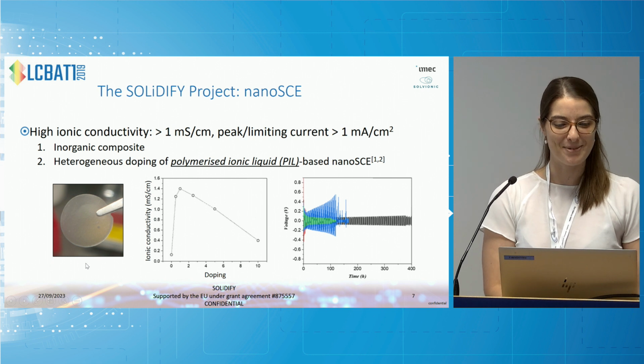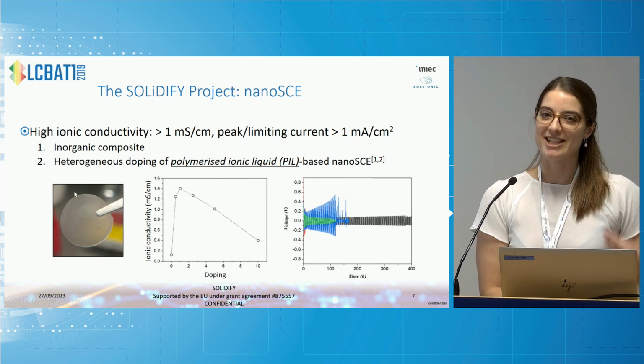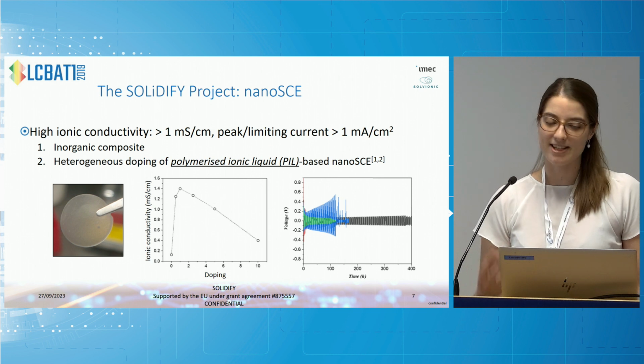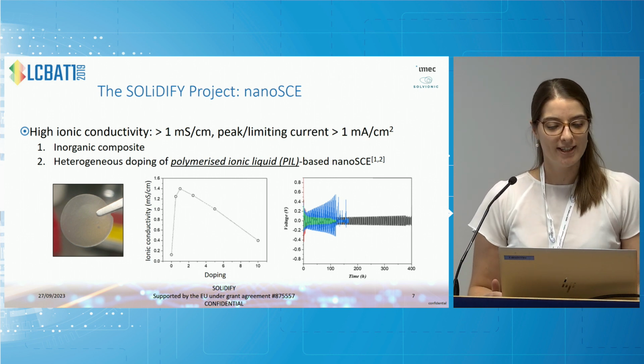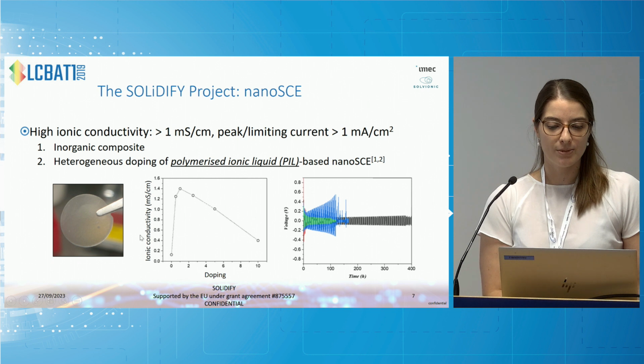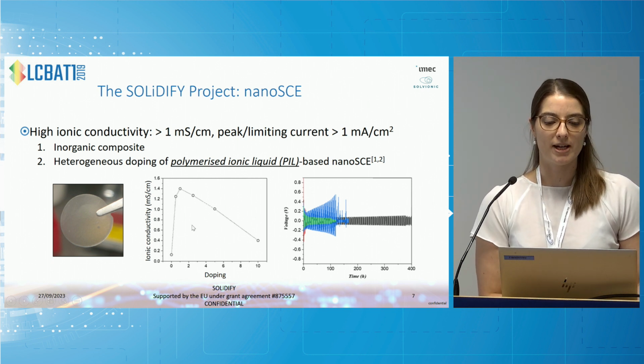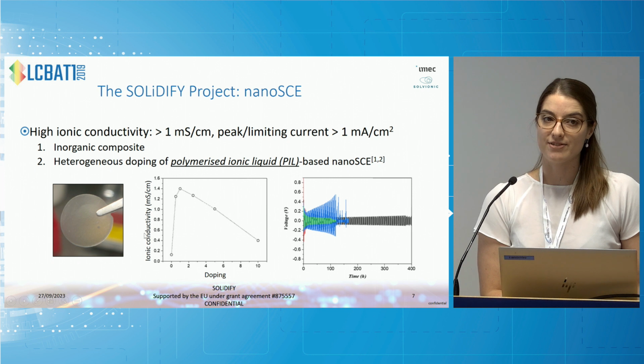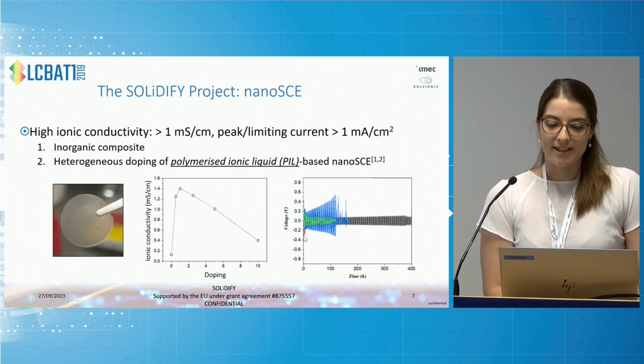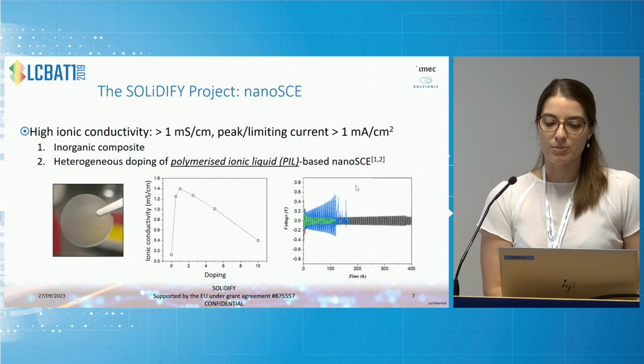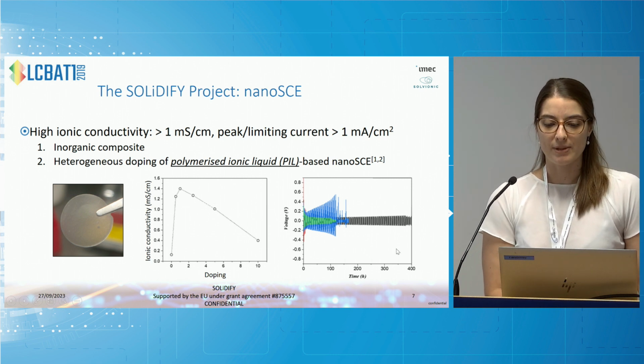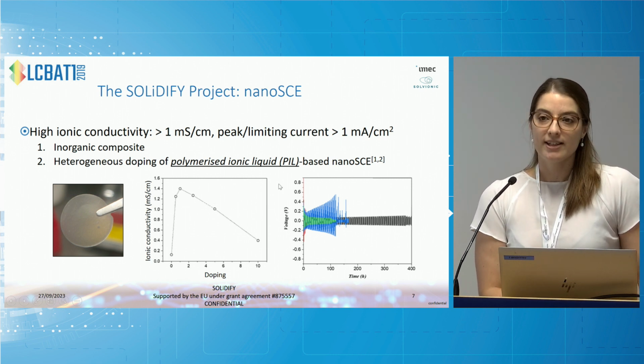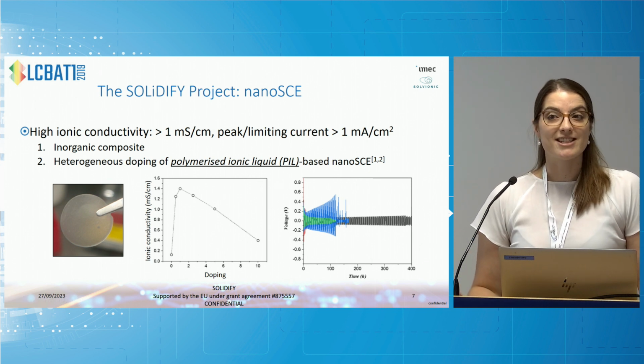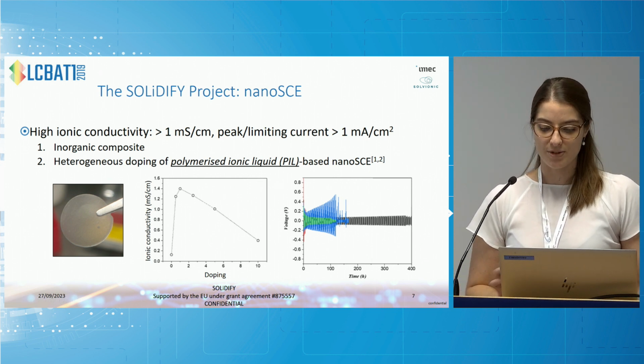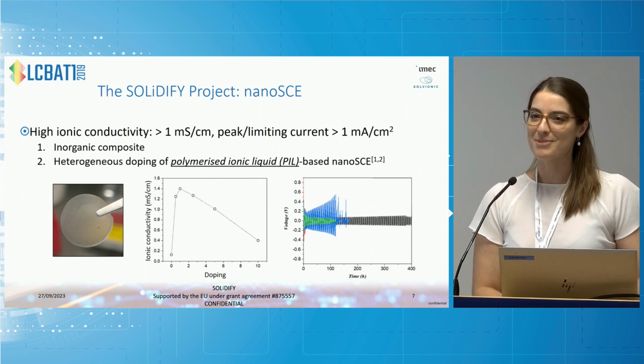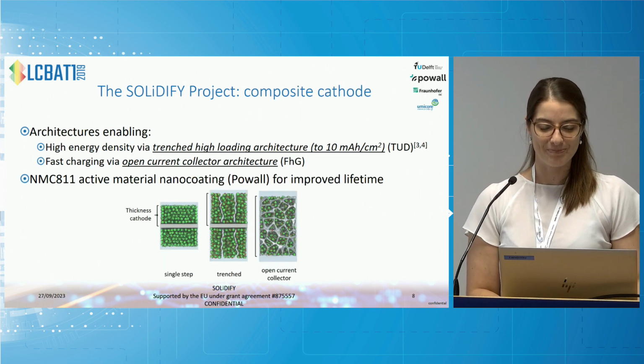I think it depends on the person, but if you saw, let's say, the preliminary materials, these PIL electrolytes can be quite difficult to handle, but with a certain doping we can actually improve the mechanical strength as well of this system and the ionic conductivity as well, as you can see here. And then we can see with doping as well, we've improved the lifetime or the cyclability of this electrolyte as well. There will be more information in a topical session later today on the electrolyte, so I won't go too far today, but please make sure you also attend this topical session.